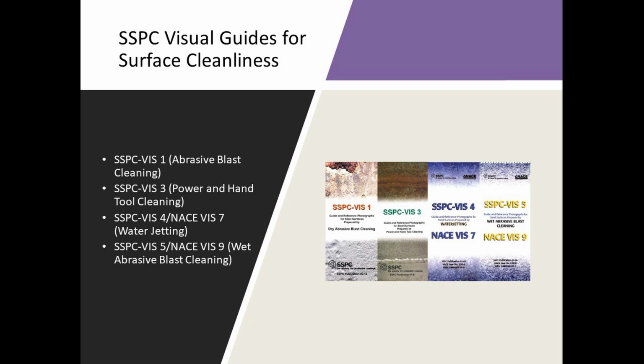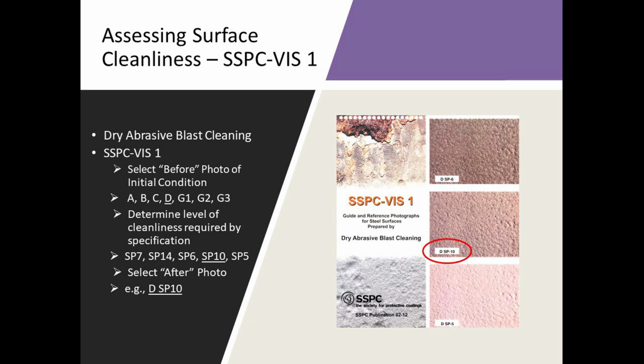Because my time is limited here, I'm only going to focus on SSPC VIS 1, which is for dry abrasive blast cleaning. Basically, you choose the representative initial condition of the steel. For example, let's say it's rusted and pitted. Look at your specification, it requires a near white blast. So we look at this picture in the visual guide and ask, does my surface look like this or better? If it does, we're good to go. If it has a greater amount of staining or less quality, then we have to do additional work.